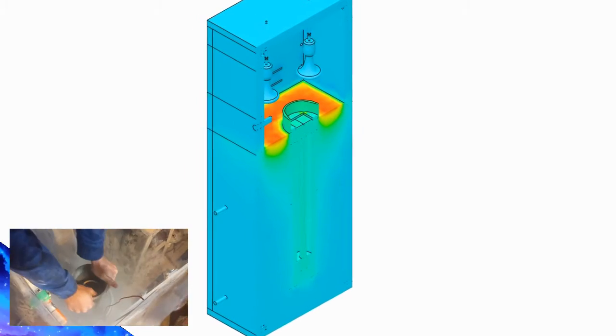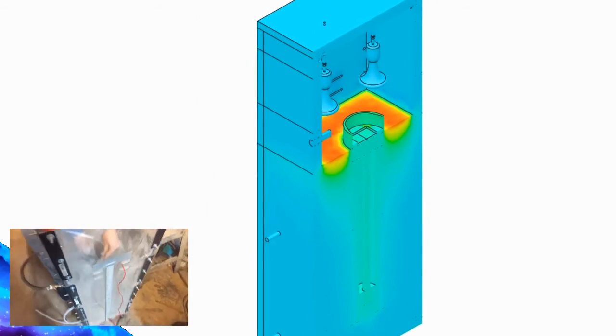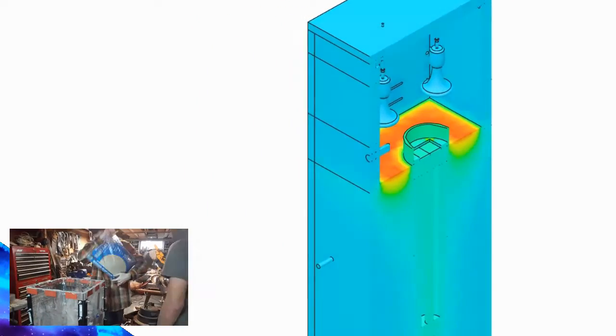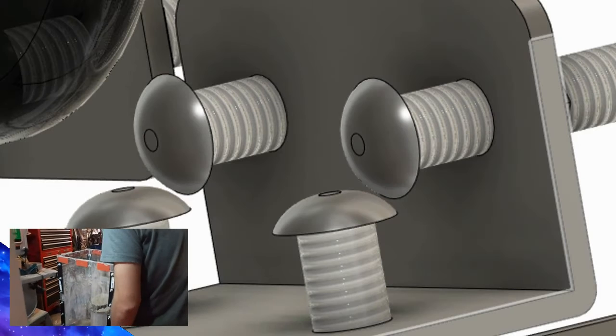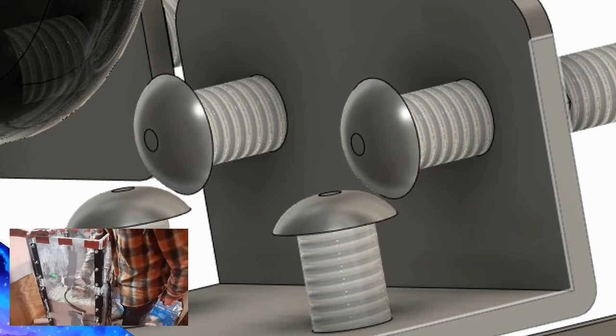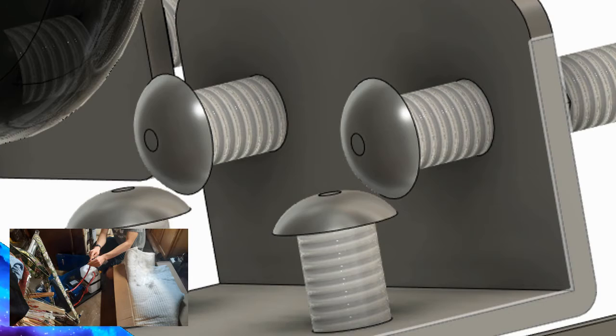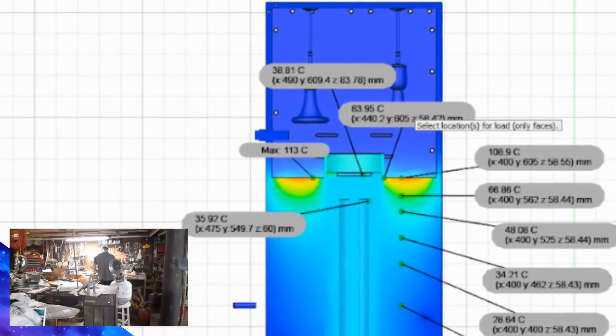To predict the results of the experiment, we ran a thermal simulation in Fusion 360 of the test rig and mock thermoelectric helical anchor. For simplicity, nuts and bolts in the acrylic box were ignored, and contacts were defined within a tolerance of 0.1 millimeters. Also, the energy from the heat lamps was applied evenly on all the exposed portions of the sand and mock anchor with nothing lost in the vacuum.